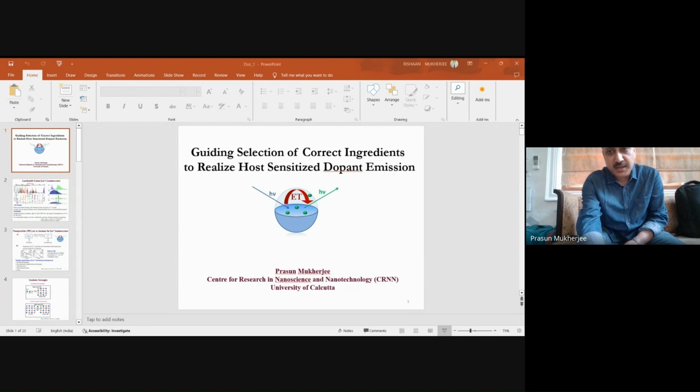using this kind of, let's say, terbium-doped zinc sulfide nanoparticle, one can realize emission in the UV, blue and green regions from a single luminescent system having two luminescent centers. Now, however, to use lanthanide luminescence for practical purposes, the intrinsic challenges are their inefficient direct excitation and the environment-induced emission quenching processes. To overcome these challenges, one way is to dope these lanthanide cations in